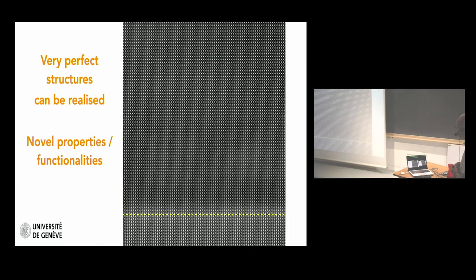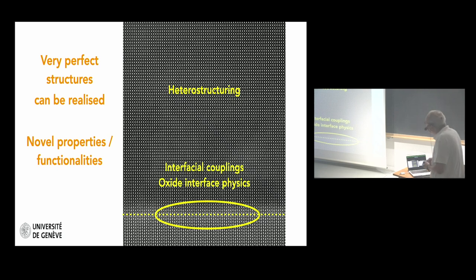And you see here one example of a film which has been grown on a substrate, and in view of the quality of the material, you need to put this yellow line to indicate the interface between the substrate and the film. Now, why do we do this? Because we would like to find ideally novel properties or novel functionalities, and these novel properties can come from the heterostructuring itself, because you can combine different materials in a heterostructure, but they can also come from interfacial couplings that can occur at oxide interfaces, and this field has been sometimes named oxide interface physics.